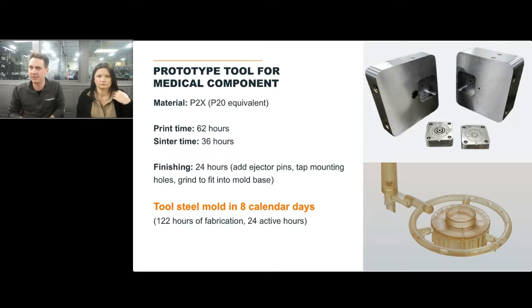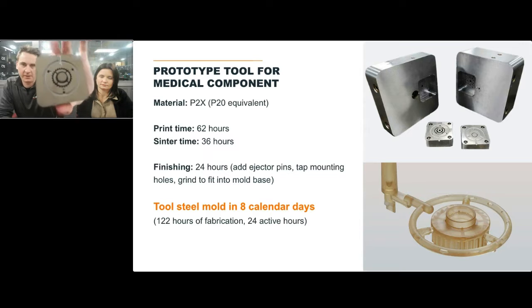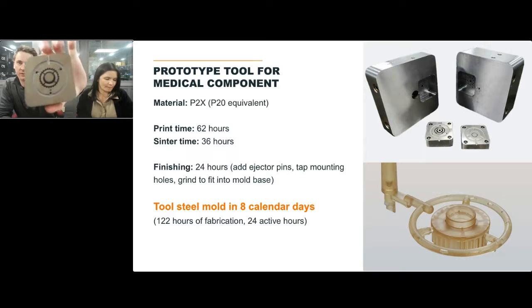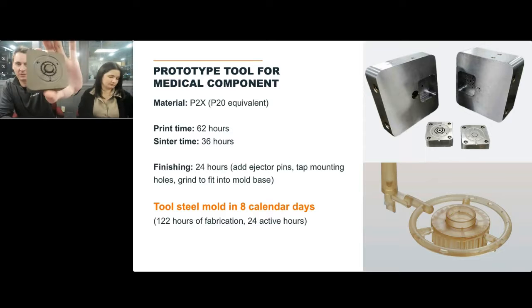Here they actually used the P2X material, or P20 equivalent material. This was earlier on in the Mantle process, printing in about 62 hours, all unattended. So in about 2 or 3 days, it went in the furnace for about a day and a half, and then we did 24 hours of finishing on these tools, which was finishing those ejector pins, tapping the mounting holes on the bottom surface here, and then grinding it to fit into the mold base.